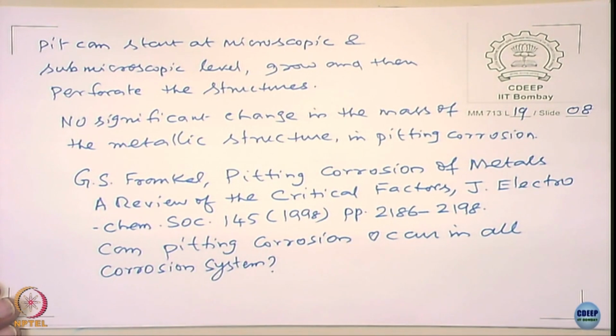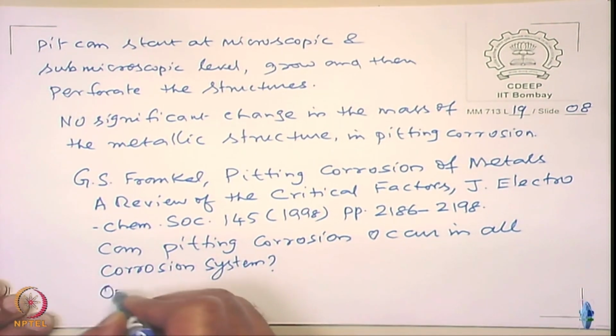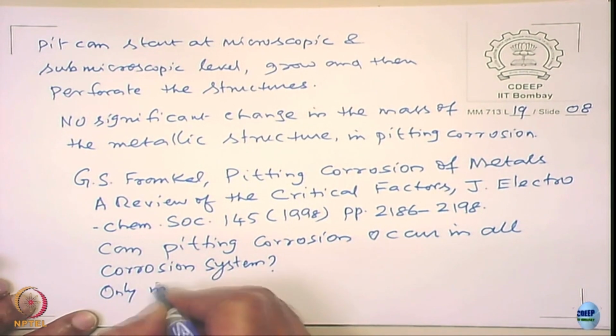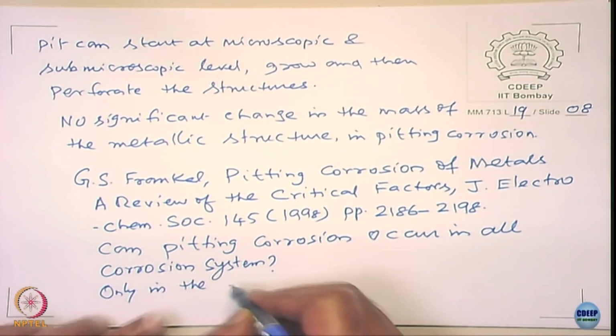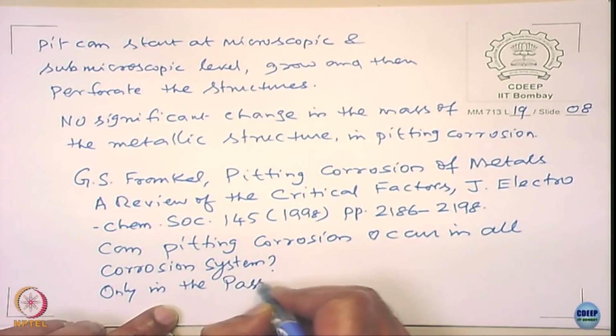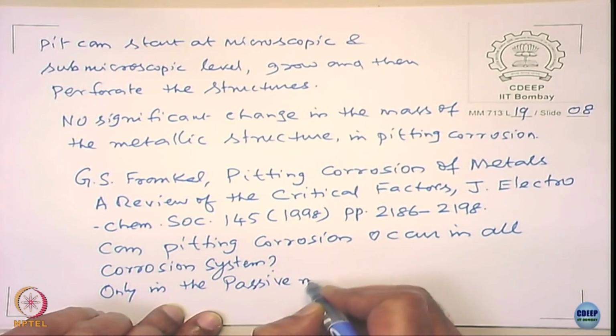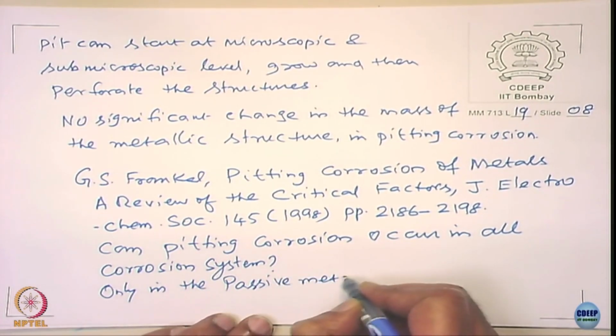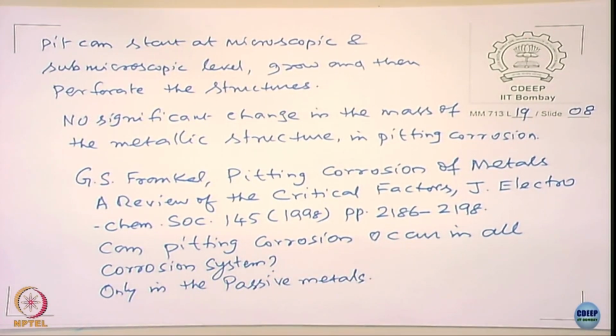The answer is that it happens only in passive systems, in passive metals. If the metals do not passivate, there would be no pitting. Passivation is an important criterion.